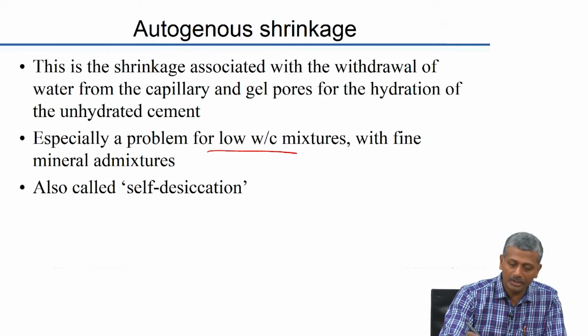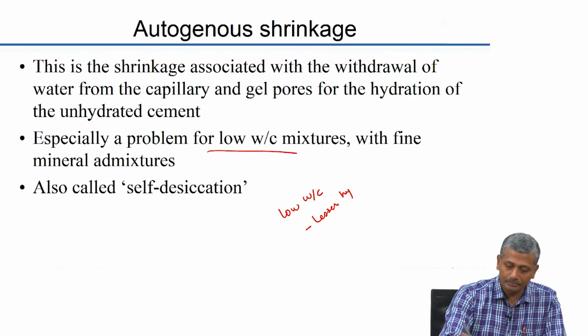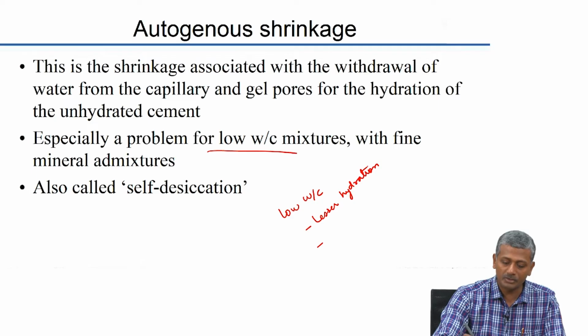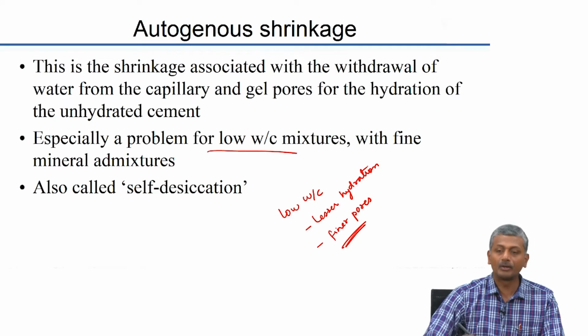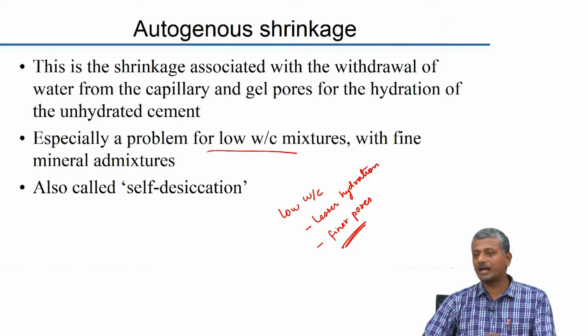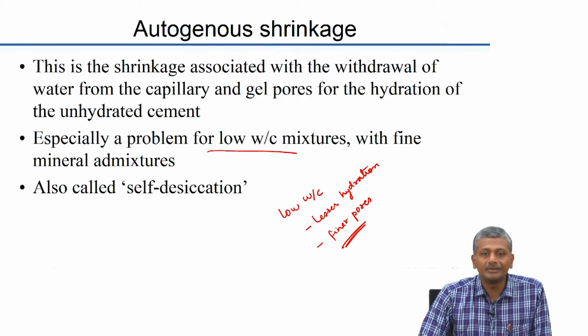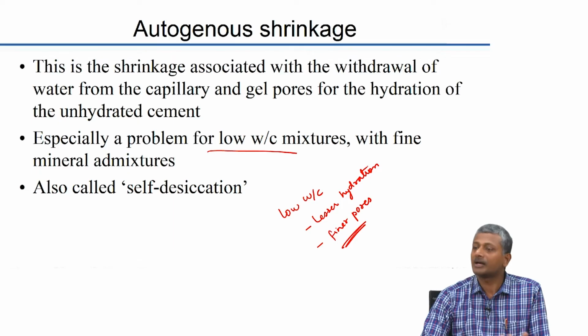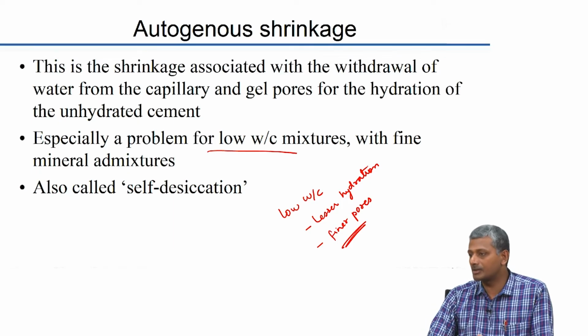Okay. So, essentially low water cement ratio is responsible for lesser hydration, and then second it produces finer pores. So, both these factors contribute to autogenous shrinkage. In fact, when you think about high strength or high performance concretes, the extent of autogenous shrinkage can be much higher than the extent of drying shrinkage.